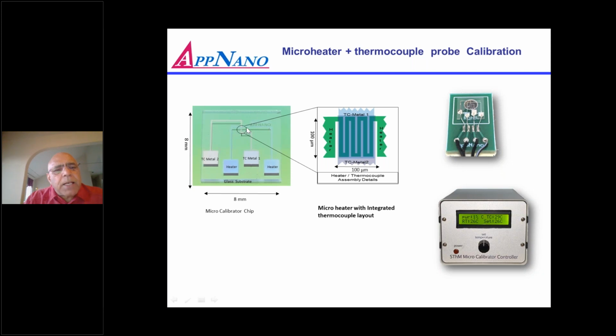integrated thermocouple and heater assembly. This assembly is on a glass substrate so that the heat is localized. So the whole idea was that we want to localize the heat and go to high temperature. So that's why we want to have the insulating substrate, and we don't want to have a heater which can heat the whole stage and can impact your scanner. If the heater is a very large dimension, it can even destroy the scanner.